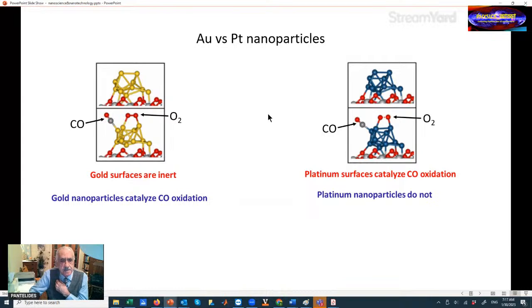Another example of nanoparticles that made a little noise: gold surfaces, as you know, are inert. They don't interact with anything. Gold doesn't oxidize or do anything. But if you go to very small gold nanoparticles, they act as catalysts and enable CO oxidation. You can see the gold nanoparticle here, a CO molecule attached to it, and an oxygen molecule from the atmosphere attached to it. And they managed to get them together to form carbon dioxide, which is good, unlike CO, which is poisonous and is generated on many different occasions, and you want to capture it into carbon dioxide.